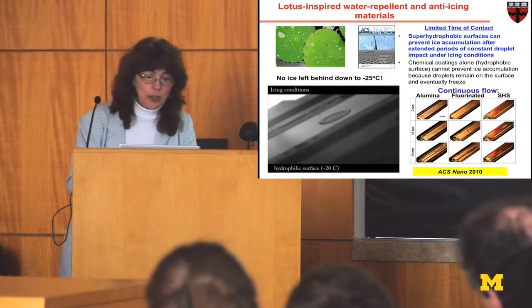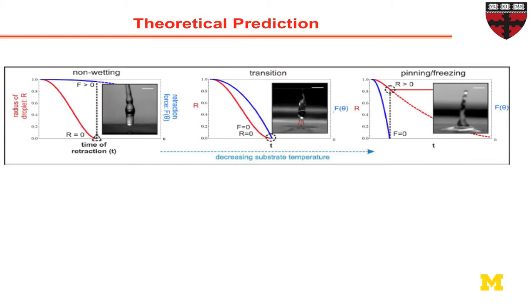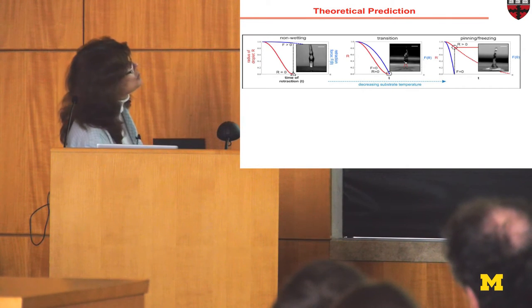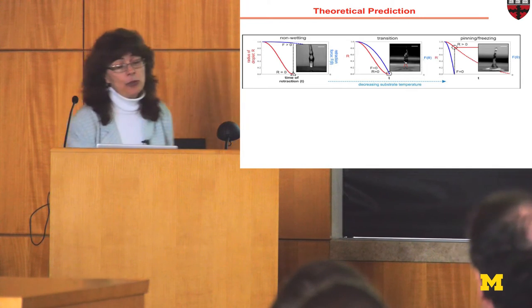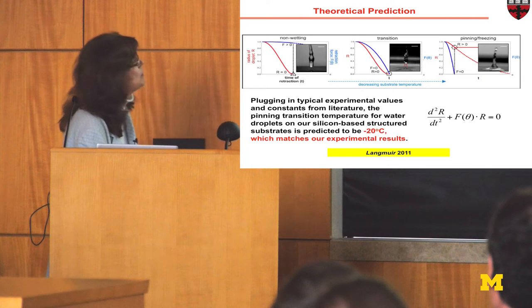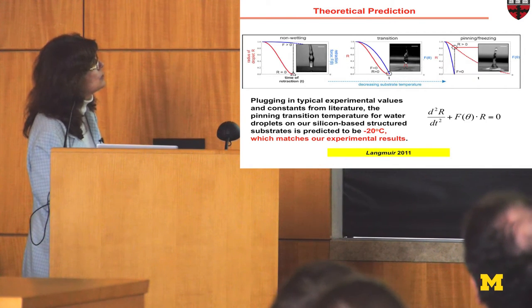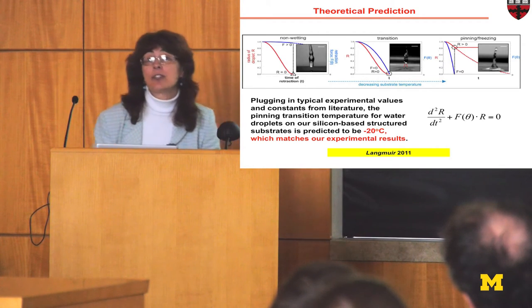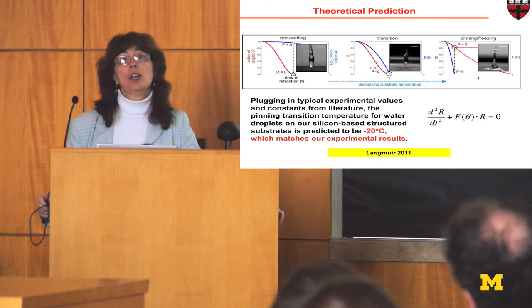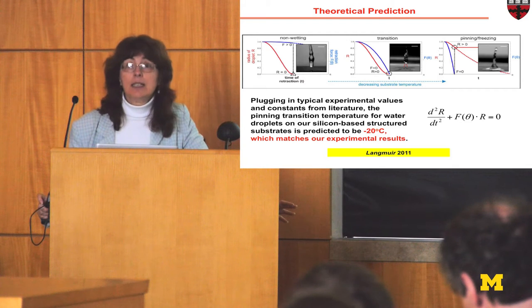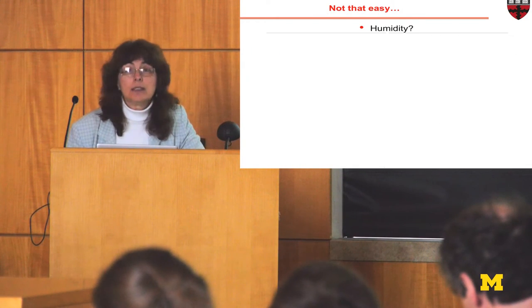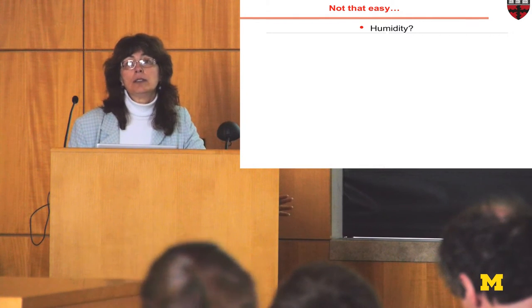substrate. So very nice, and there are a lot of theoretical studies of this phenomenon, just understanding at which moment the force on the droplet that comes together, it's related to friction, and also changes in the thermal transfer in the system. It's a multi-parameter system that one has to model, and at which moment it begins to fail, at which temperature there would actually not be enough time for the droplet to withdraw from the surface, and we've done it, and we were very happy to see that theory predicted about minus 20 degrees C, and experimental results showed us minus 25 degrees C. Great, down to minus 25 degrees, no ice formation on these surfaces. Everything nice, as long as we realize that these are done at very low humidity.